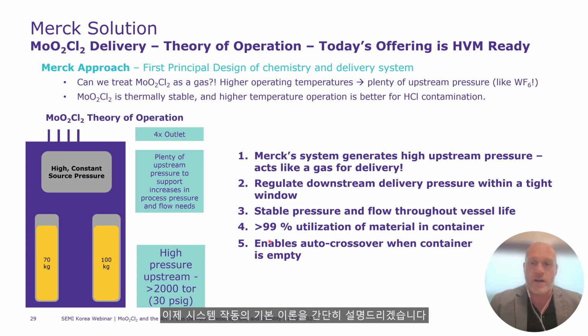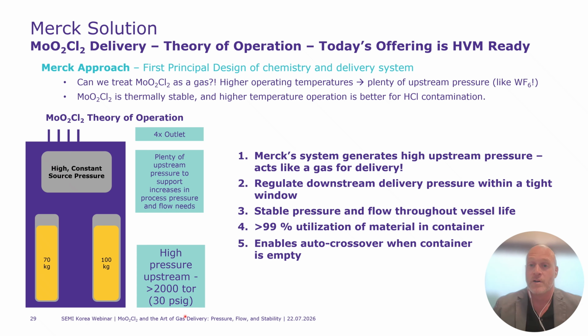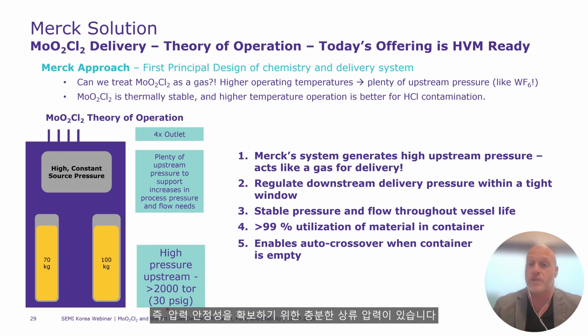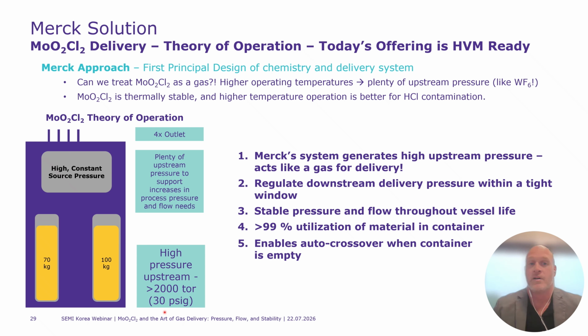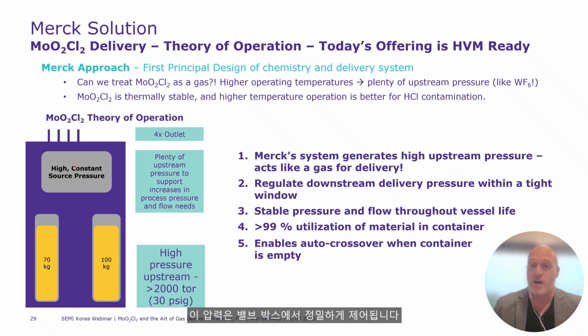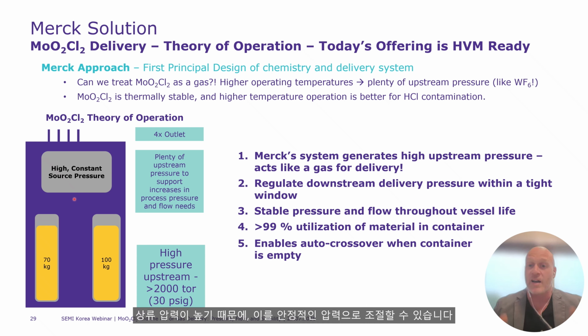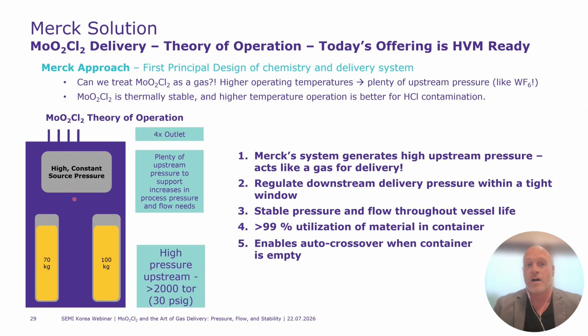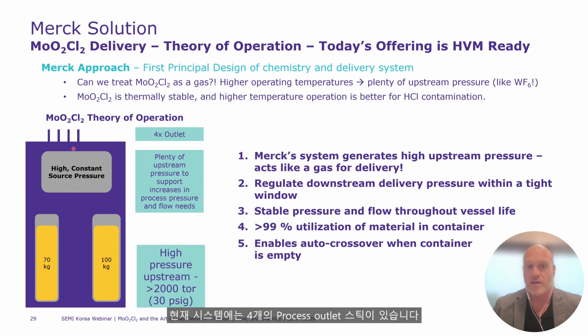So, really quick, fundamental theory of operation for our system. Again, we have our pressure source, and you're driving heat into that. We're at pressures of greater than 2,000 torr, so we have plenty of upstream pressure for pressure stability. We control that pressure in our valve box. We're managing that high upstream pressure to get a rock steady pressure, so we're down regulating to a rock steady pressure and flow for our customers. And then we have 4 sticks available today.